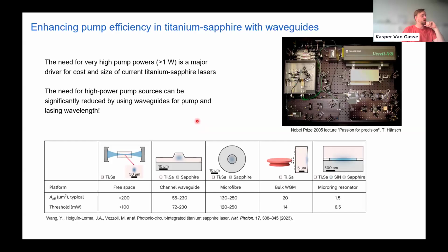So people have been working on that in many ways. For example, pulsed laser deposited waveguides, even titanium sapphire fibers, titanium sapphire micro whispering gallery mode resonators. And then before our work, people even bonded titanium sapphire crystals on silicon nitride. So what does this do? We try to constantly shrink the effective mode area, and that allows us to have much higher intensities for the same pump power, or dramatically reduce the pump power to achieve lasing, for example. All right, but so far, with all these approaches, a real high-performance titanium sapphire laser that can be pumped with a simple laser diode has not been demonstrated.